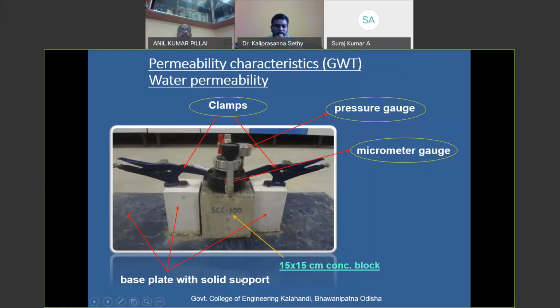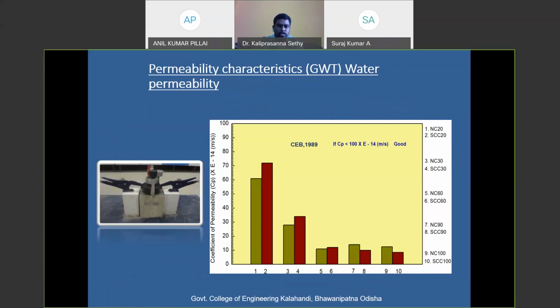There is a base plate with solid support and clamps which tighten the 15 by 15 centimeter cube, that is the block, and with a particular pressure, the water is injected into the concrete. Readings are taken at 2-minute intervals up to 30 minutes, and at 5-minute intervals up to 1 hour. And with the help of Darcy's law, we calculated the coefficient of permeability for this concrete, and we found this result. You can see this is the NC 20, I mean M20.